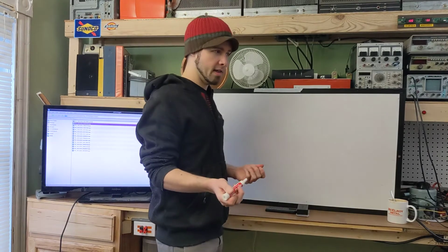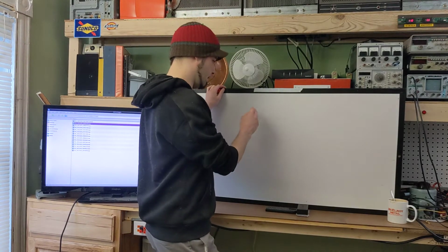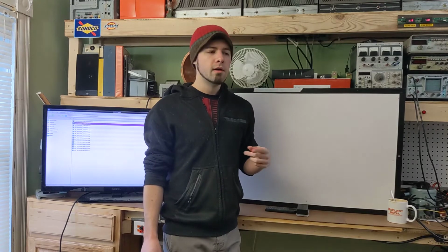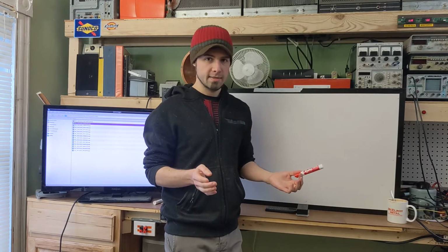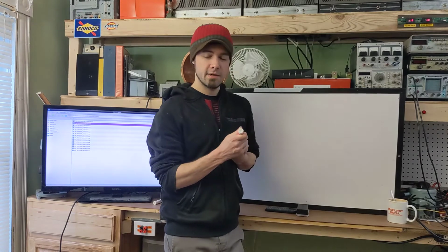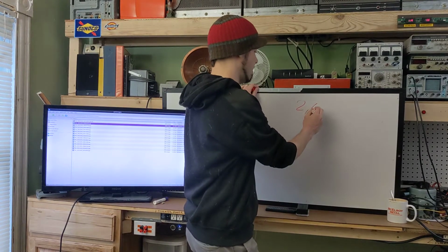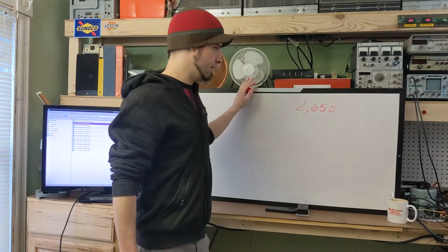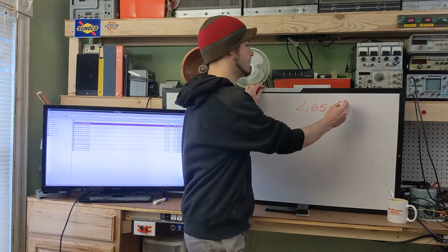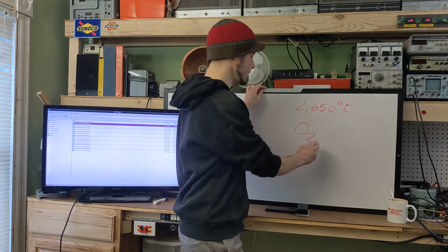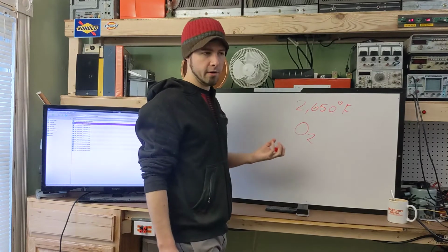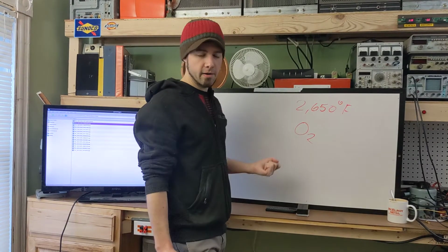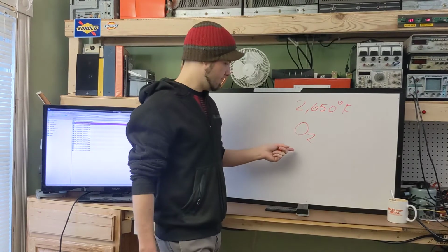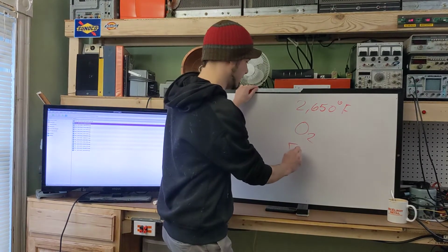So a tire obviously has steel wires in it. So your typical tire has the belting that's in the tire, the reinforcing steel. When they drop the tire into the cement kiln, that steel actually oxidizes. It burns. This 2,650 degrees Fahrenheit is hot enough in an oxidizing environment. This atmosphere is not only this hot, but it has excess oxygen. And that temperature with oxygen is enough to get the iron in the steel to combust. And that iron actually provides energy to the kiln because it's combusting and it's creating iron oxide,